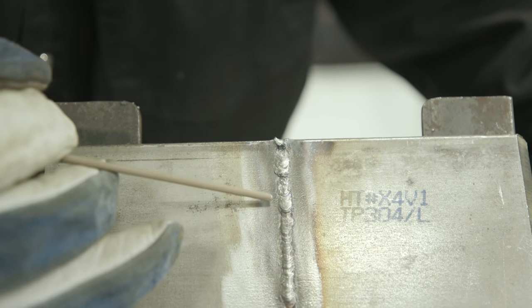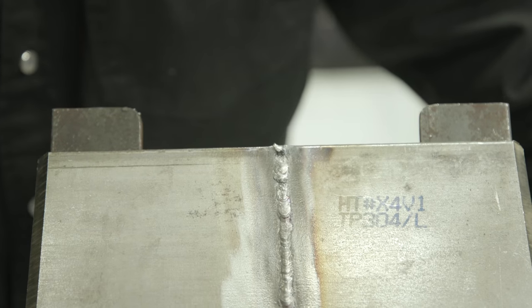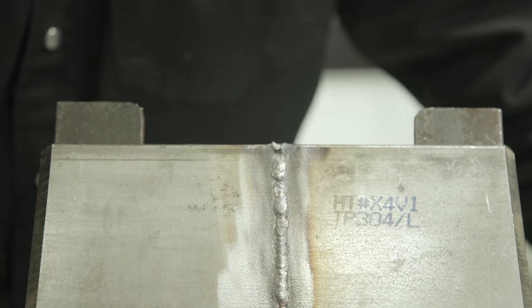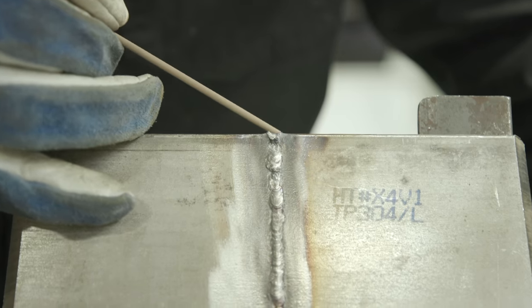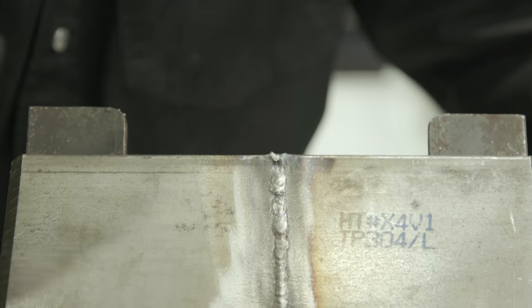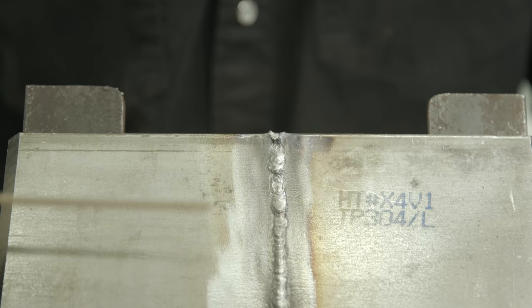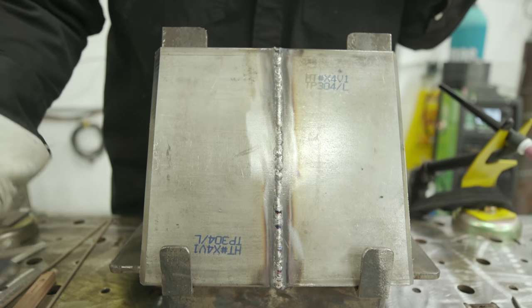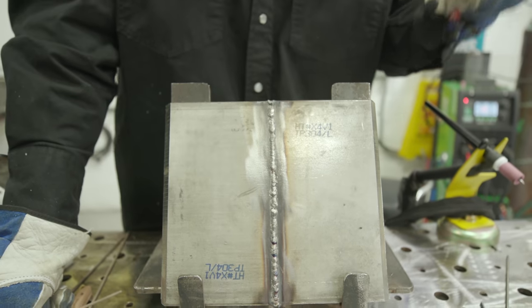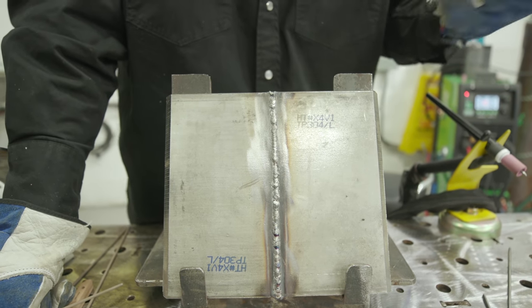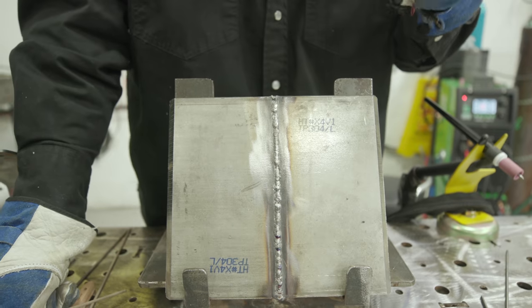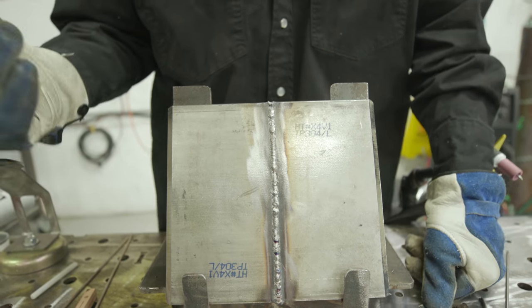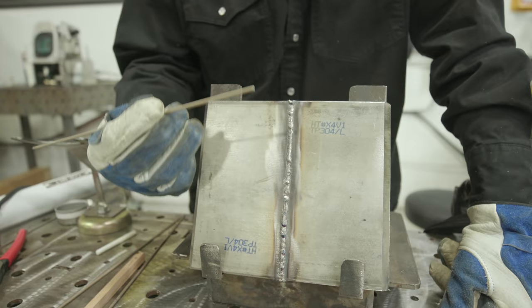Got a little bit unsteady right here with my amperage, but still passable, still good. This is where you probably saw the camera - it closed up and I was like oh crap, but I just kept going through it and actually broke it all down. That still would be a good weld. We're ready for our next pass. I'm going with this rod still because if you leave your purge in there when you're doing your hot pass, in case you blow through you got to have that purge to protect the back side. Same concept, just use this rod still.